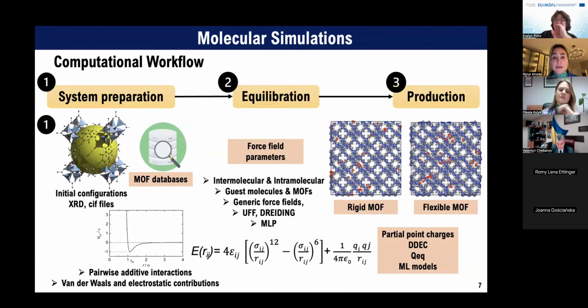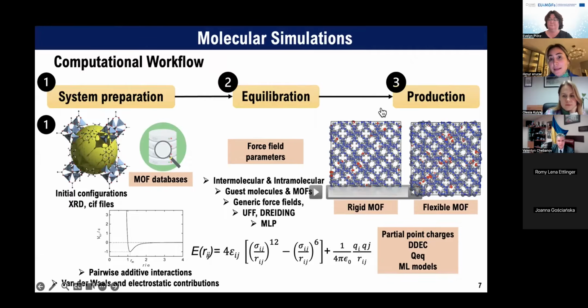For the Coulombic interactions, we need partial point charges for the atoms of the MOF structures. So these partial charges can be identified from DFT-based calculations or some machine learning models as well, or some empirical models like charge equilibration. You also need these charge values. After system preparation, you have to equilibrate your system, and finally, you have the production data.